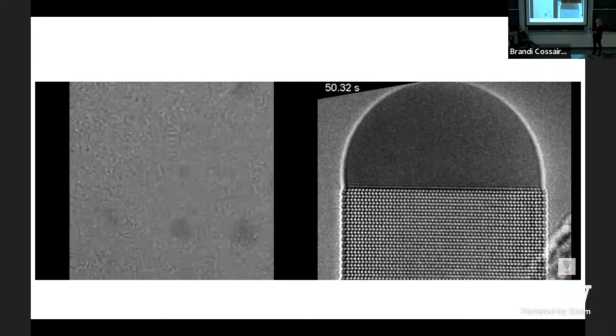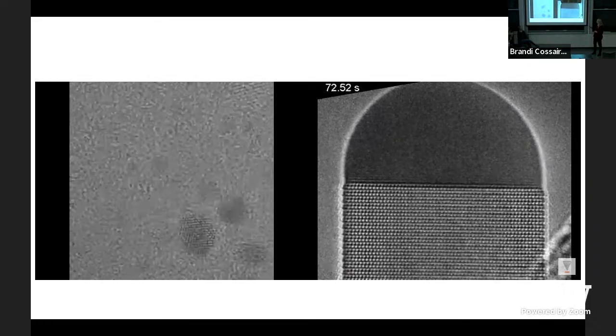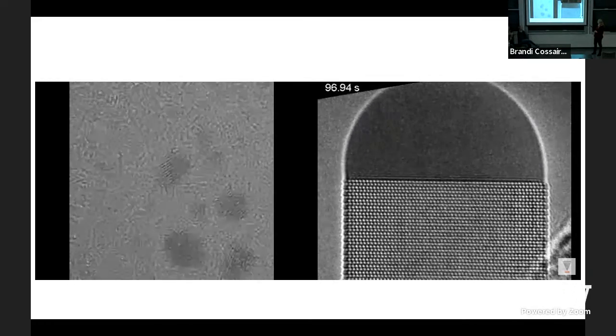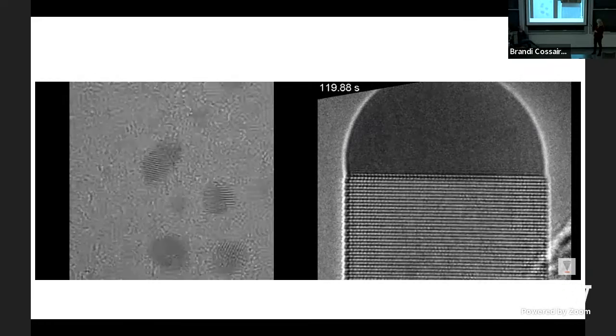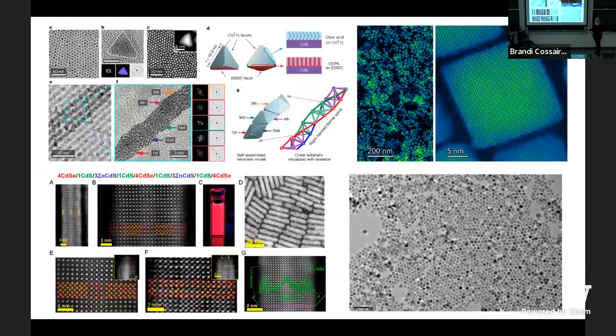So this is an example of nanocrystals forming in solution. This is atom by atom layered growth of a nanomaterial. So we can see them form via electron microscopy. We can look at individual atoms if we have high enough resolution. We can look at assembly. And so really building up into actually looking at these materials, understanding that they are this size has allowed this field to expand quite substantially. I'm going to hand this off now to Jessica, and she'll tell you about quantum confinement.